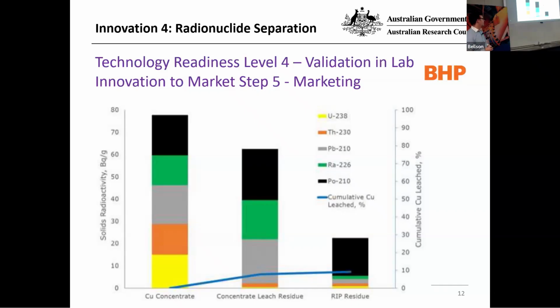This graph, which was presented at the 2022 Copper Conference in Santiago, shows on the y-axis the radioactivity of a copper concentrate in terms of the different radionuclides: uranium, thorium, lead-210, radium-226, polonium-210. If you contact that with sulfuric acid, which is the residue of the second bar, you can see that the uranium and thorium can be leached out directly. However, the lead, radium, and polonium don't leach out in that process, so the radiation still stays reasonably high.